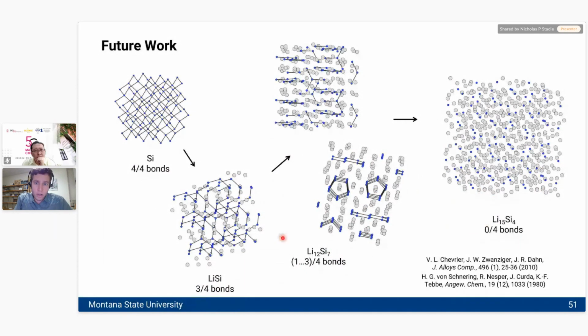So future work in our group is going to be to try to harness just this initial reaction here, to try to stop it before we start cutting and breaking all of the silicon bonds in the material. We think that this reaction should be much easier to reverse reliably over millions of cycles, like Jeff Dahn's graphite cell. Okay, but stopping it here is very difficult.